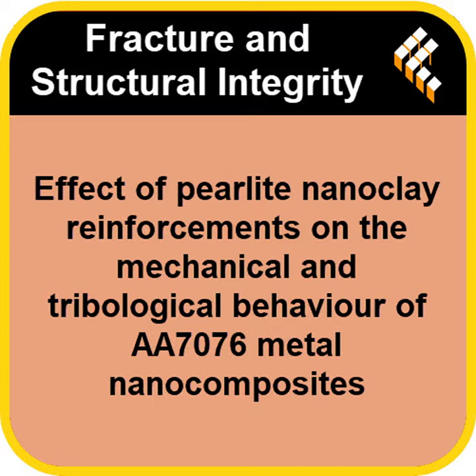Okay, let's check the tape then. Section 2, microscopic validation. Did this relatively simple stirring method actually work? Did they get that even mix? Well, according to the results, yes. A resounding success, actually. They used scanning electron microscopy, SEM, and also energy dispersive X-ray EDS analysis. The SEM pictures, the micrographs, they confirmed the nanoparticles were almost entirely uniformly distributed, mostly along the grain boundaries of the aluminum matrix. And the big worries, clumping, agglomeration, or trapped air bubbles, porosity. Those can kill the properties.